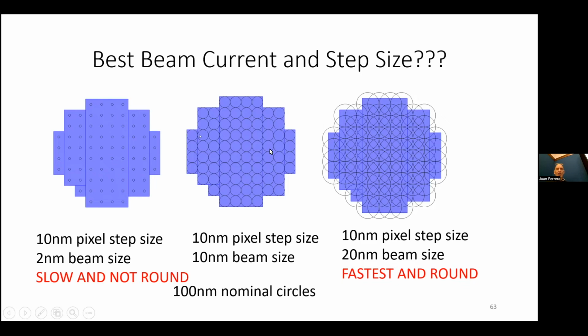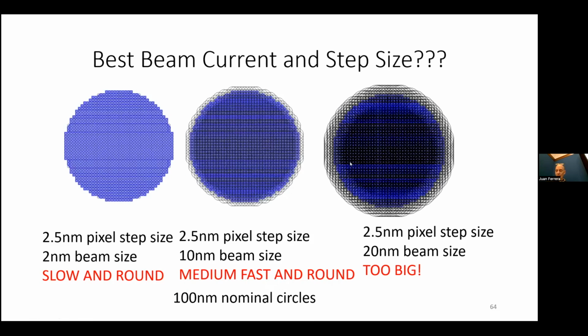On the other hand, if we pick our pixel size and our beam diameter size to be equal, that may work very well for us as the common default to start with. On the other hand, maybe we want to go really fast and we know a little bit more about what we're doing, and we say, let's go with a beam size that's twice our pixel size. We intentionally round off some of these corners. We make our feature more circular, and we go fast all at the same time.